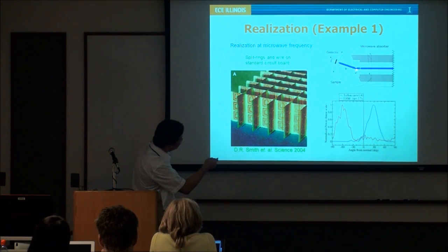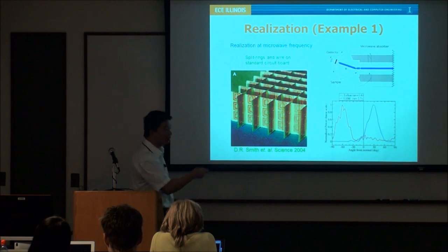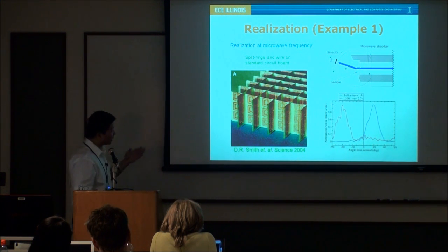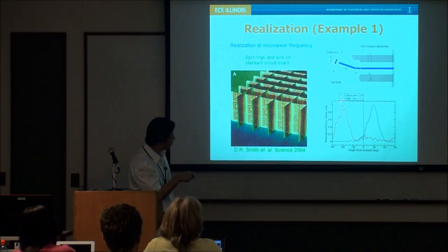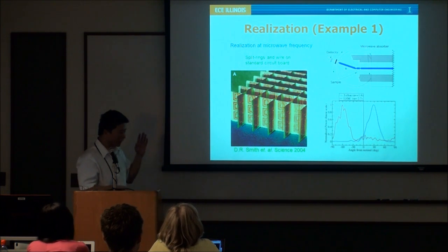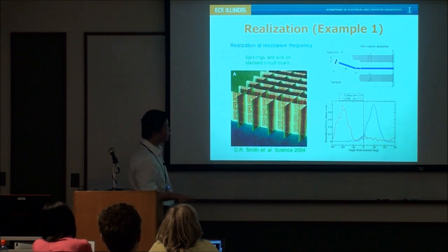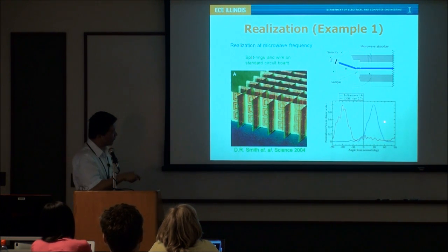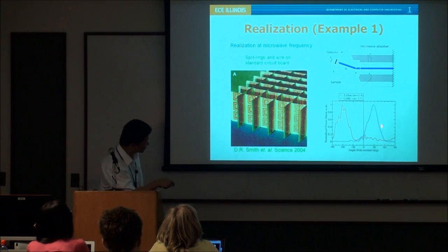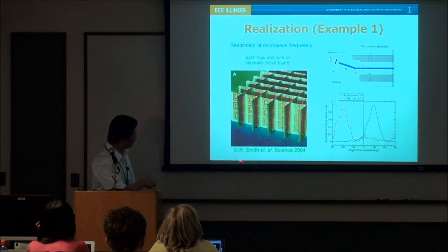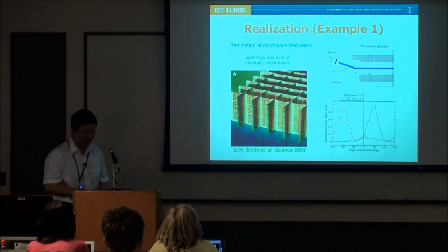You would expect your refraction to follow this kind of direction. This is called a positive refraction. But instead of that, they have measured the so-called left-handed or negative refraction by measuring the actual refraction at these angles. So these are the actual results. This is the actual positive refraction, which is the Teflon case. But for these materials, you would expect to see this kind of refraction pattern measured at very different angles.